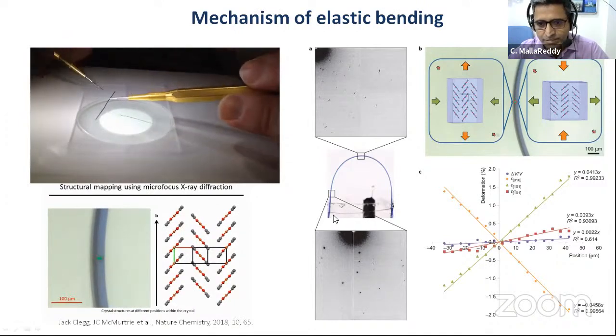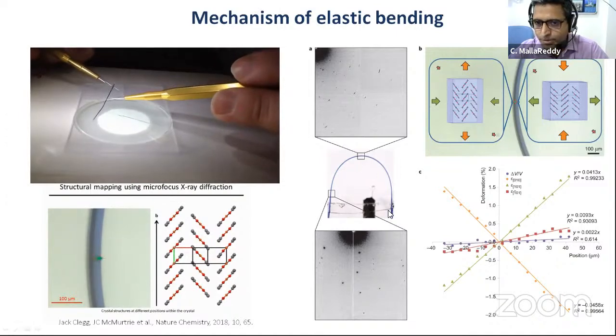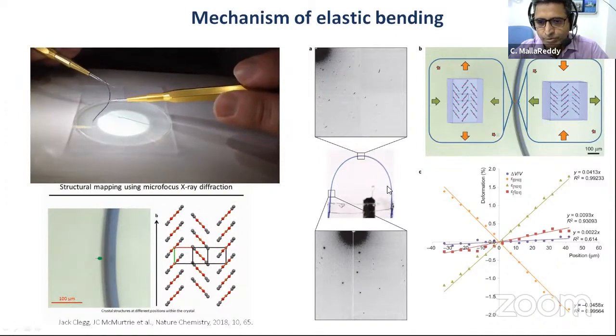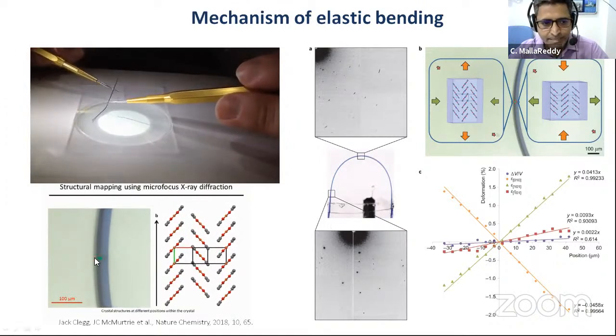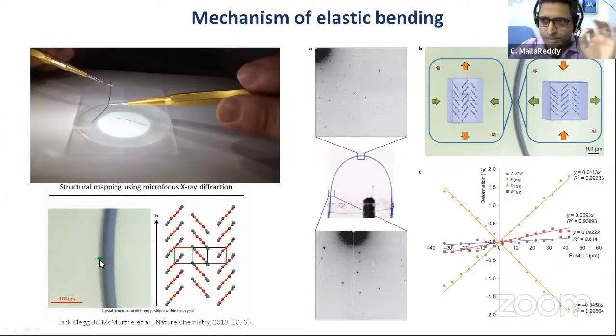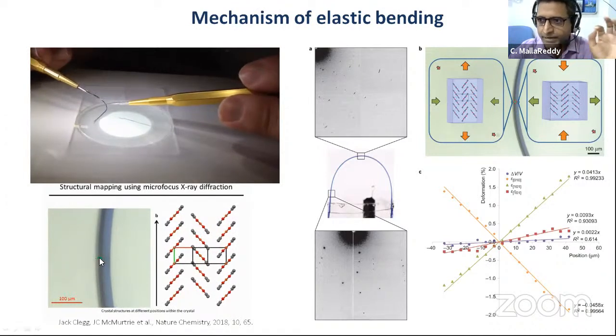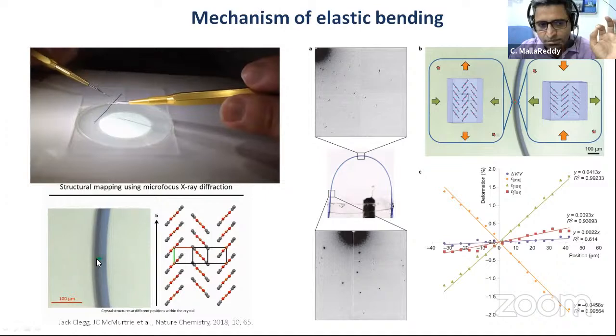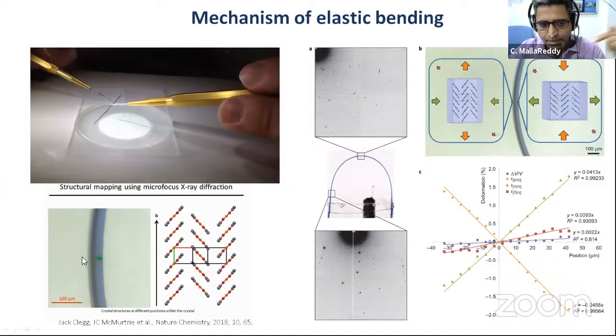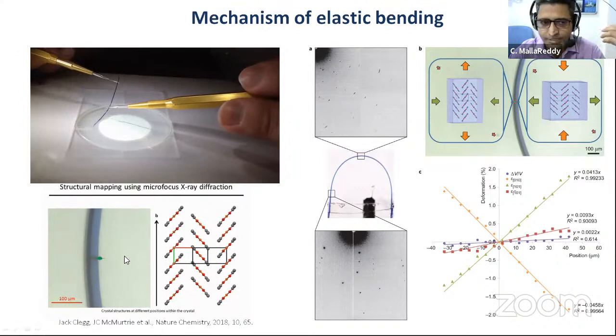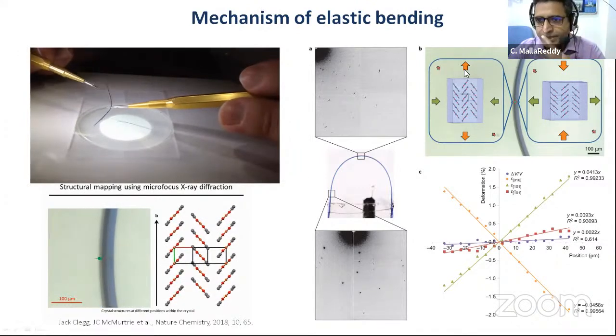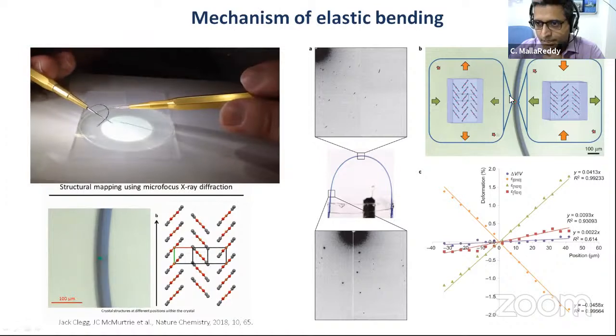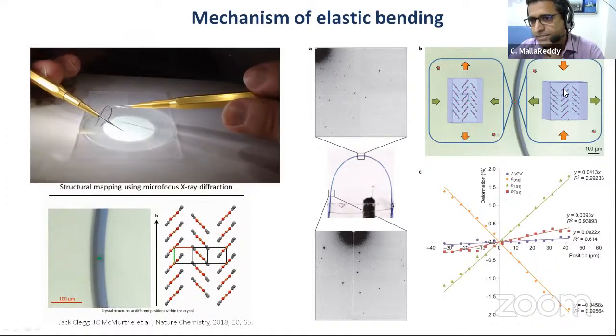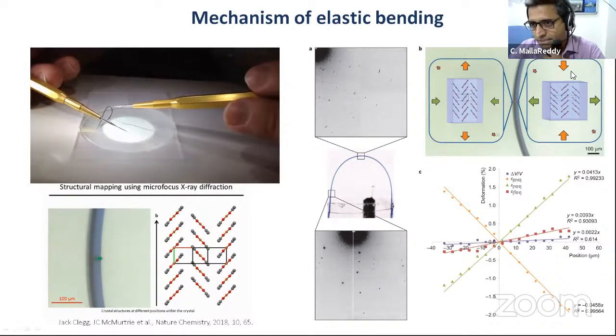You can see the diffraction. This is a crystal mounted on the loop on a diffractometer, and then you make a loop. This bluish one is the crystal, and then you diffract. So they have basically moved the diffraction spot very little, and then collected a lot of spots along this line, along this axis, and then they got the crystal structures at each point, and then they saw that on the outer side you have an elongation along this direction, the needle direction, and then there is a compression along this same needle direction.